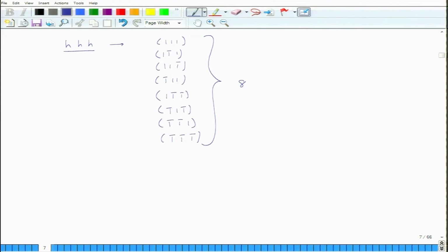So, similarly for a cube, if you take HKL kind of planes it will be 48. If you look at HHL, it will be 24. If you look at HK0, it will be 24, and so on and so forth. Okay. So, this is for a cube. Okay. Now, if I do the same exercise in a tetragonal system, let us say I take a tetragon.